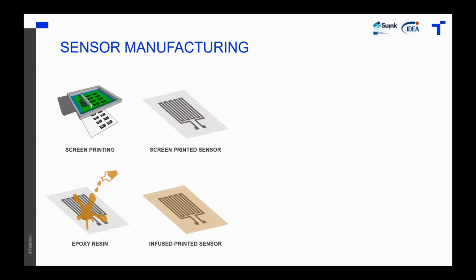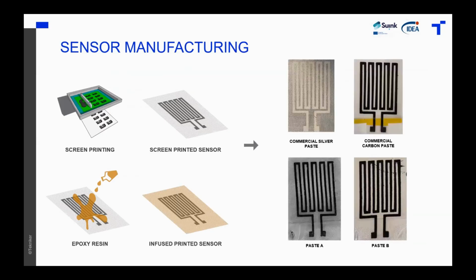The next step was to manufacture the sensors. We screen print the sensors onto the glass fiber substrate. We glue them, and after that, to protect the sensor and avoid humidity effects, for example, we get them infused in an epoxy resin, as we can see on the screen, and we obtain all these sensors.